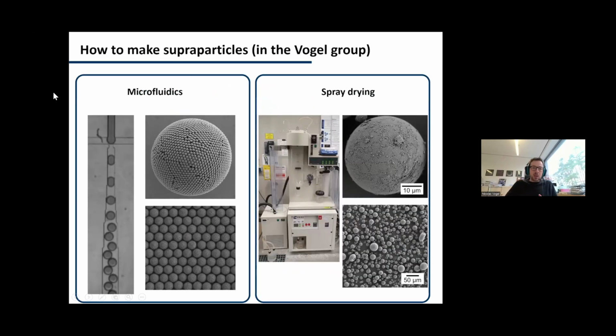In our lab, at least, we have, in a sense, two technologies. One is droplet-based microfluidics that you see here on the left-hand side. So what you see here is a stream of a water-based dispersion of particles, and here you have an oil stream. And at this intersection here, the continuous stream is split up, and we have these very uniform droplets of particles. And this is, of course, very useful if you want to make defined particles and study structure property relationships in great detail, but it doesn't really come out in huge quantities, so it's not so easy to make macroscopic materials from this.